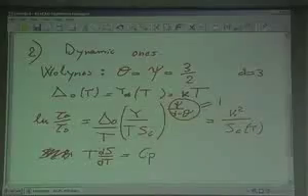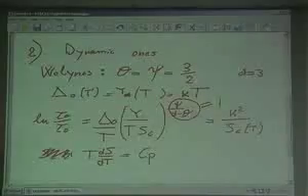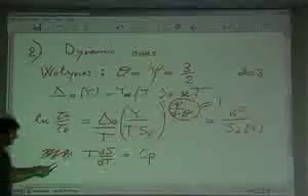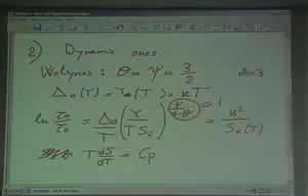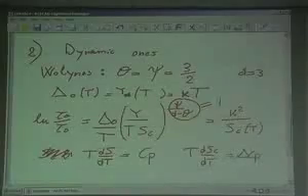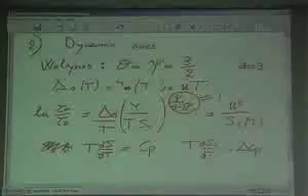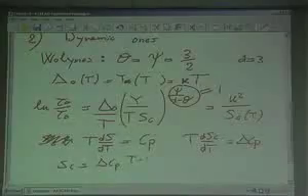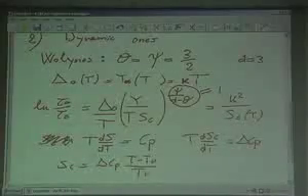So close to Tk, there is a part of the entropy that disappears, which is the configurational entropy. I know that the jump in the specific heat at Tk is just equal to T dSc/dT, where Sc is now the configurational entropy. And so now I know how I can write the configurational entropy: Sc will be just equal to delta Cp times (T minus Tk) divided by Tk.